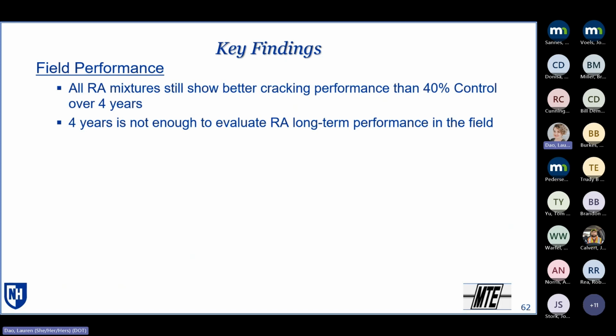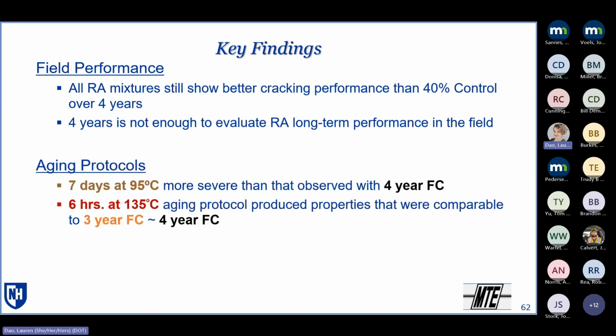For field performance, all the mixes are showing better cracking performance than our 40% control, a little bit worse than the 30%, but again, not a whole lot happening out there. So we really need to keep monitoring these over a few more years to see if we start seeing any differences in distinguishing the field performance. And then in terms of the aging protocols, this wasn't a main objective of the study, but kind of a side objective is, because we have all this data, what represents what we're seeing in the field.